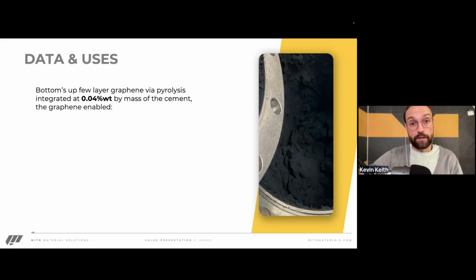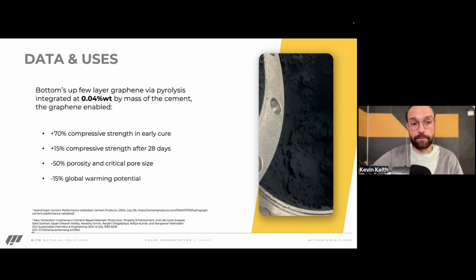Some public use cases: a bottoms-up few layer graphene made from pyrolysis was integrated at 0.04% by mass of the cement within the concrete. With this material, they were able to show an increase in compressive strength by 70% in the early cure stages. That's a pretty big jump for such a critical time in the life of concrete being set up. And after that 28-day cure cycle, it increased the compressive strength by 15%. With these metrics in mind, and with a combination of reduced porosity and critical pore size of 50%, it has the potential to reduce the global warming potential of concrete by 15% just with that little bit of material sprinkled in.